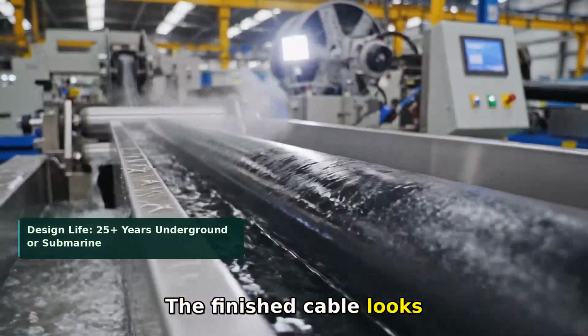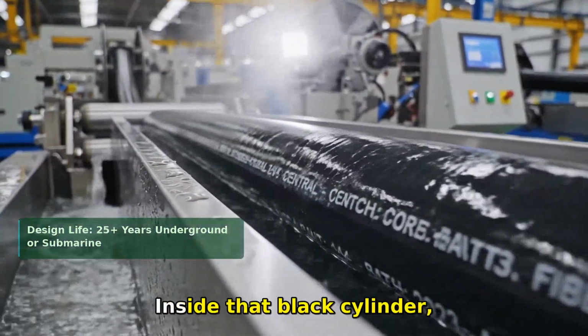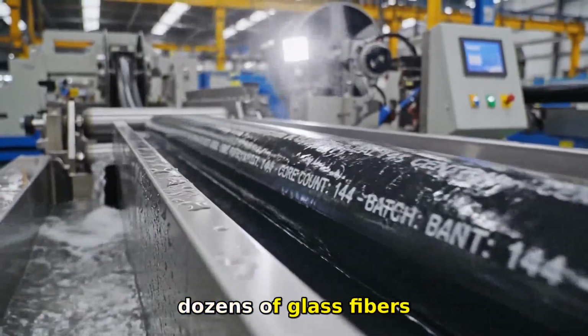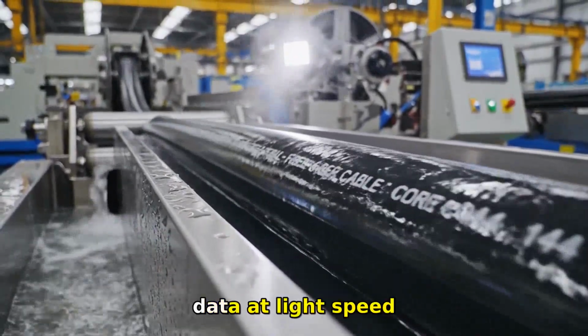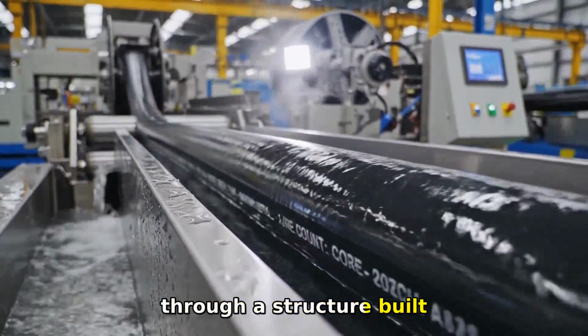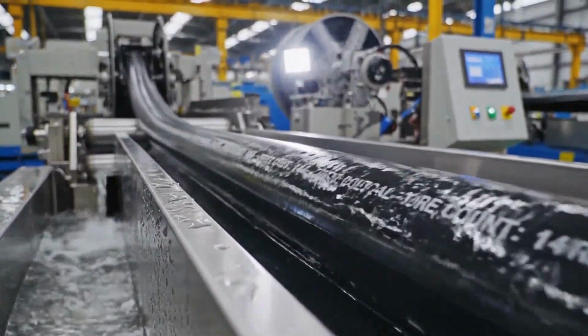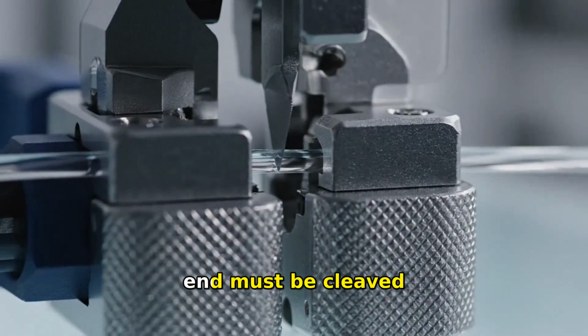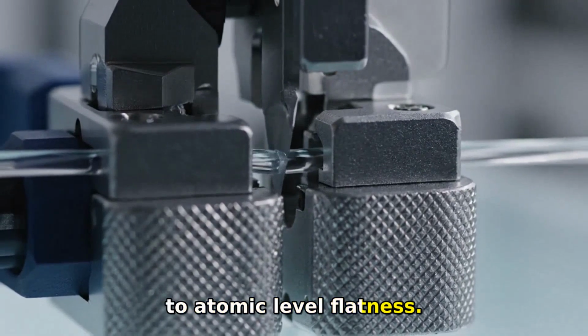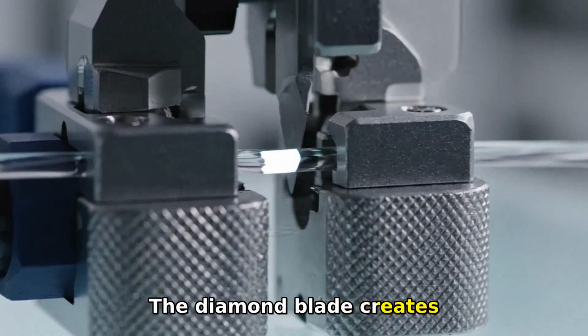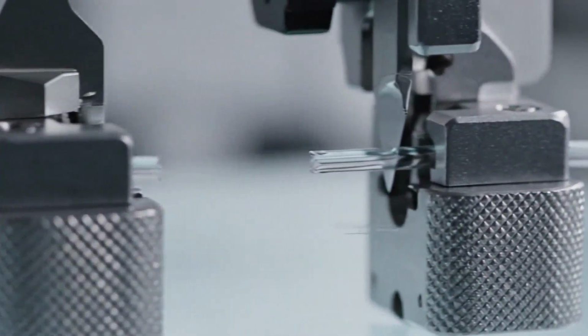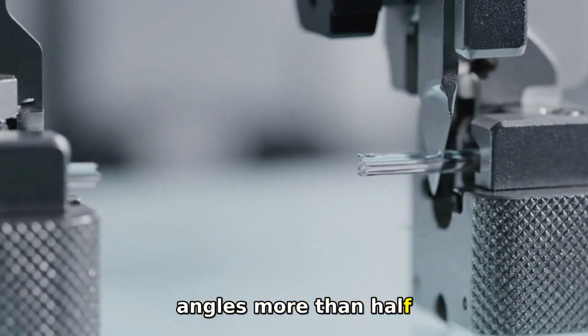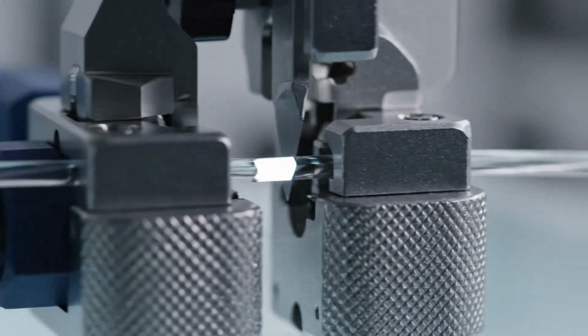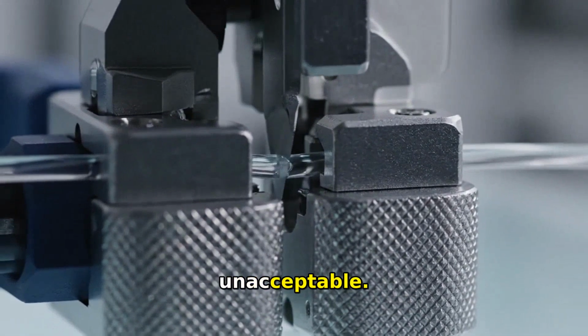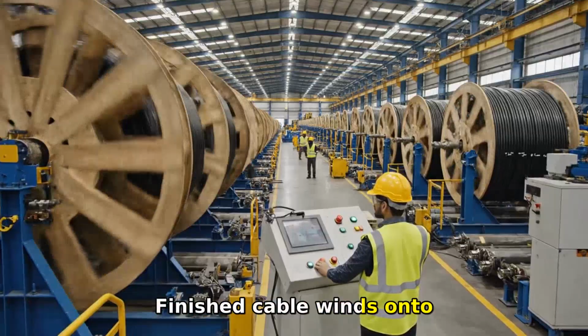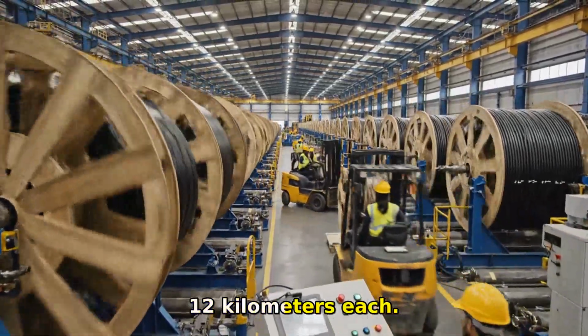The finished cable looks deceptively simple. Inside that black cylinder, dozens of glass fibers thinner than hair carry data at light speed through a structure built to survive decades underground. Before splicing, each fiber end must be cleaved to atomic-level flatness. The diamond blade creates a controlled fracture. If the end face angles more than half a degree from perpendicular, the splice loss becomes unacceptable. Finished cable winds onto reels holding 2 to 12 kilometers each.